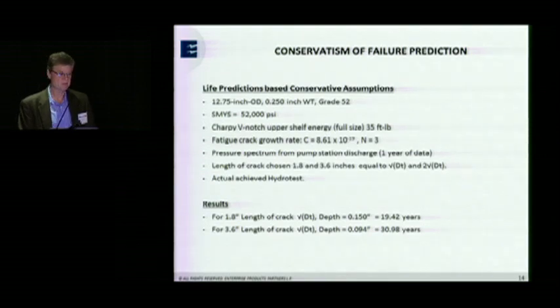You know, here's some of the conservative failure predictions for this line that have been used. And just to give you an idea of a difference, if we're using the pressure spectrum at the pump station and using the length of a 1.8 inch crack, which is equal to 1 times d square root of dt, you're getting about 20 years. And if you use the 2 times, there's an error there, it should be 2 times the square root of dt, it's about 31 years.